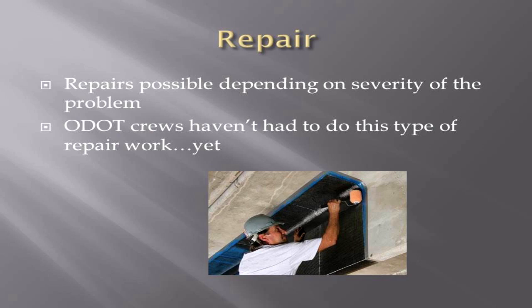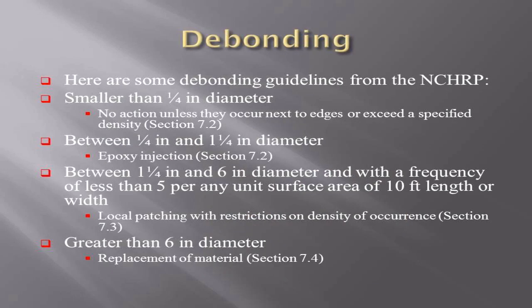Repairs are possible depending on the severity. We haven't done any repairs yet in Oregon, although we probably may have to. I don't know. Most repair will probably be done by a qualified contractor. And briefly, debonding is the most common defect that we see, so we'll give a brief overview of debonding parameters. Anything smaller than a 1/4 inch diameter, it's no big deal. Between 1/4 inch and 1 1/4 inch, you can epoxy inject it. Between 1 1/4 and 6 inches, with a frequency of less than 5 per unit surface area, 10 feet length, you can do local patching. And greater than 6 inch diameter, you should replace the material.